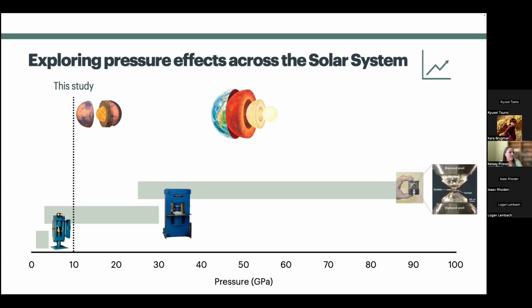But it's interesting to know that even though we're just comparing from 1 to 10 GPa, we're already finding changes in the elemental behavior. And so it's worth studying further at higher pressures to see, does that continue? Do we see more changes as we go to higher pressures, or is the change only in that 1 to 10 GPa range? And so that's the collaborations with Tulane and Harvard with the diamond anvil cell experiments. That's something that we're able to start to address for those elements that we're studying.